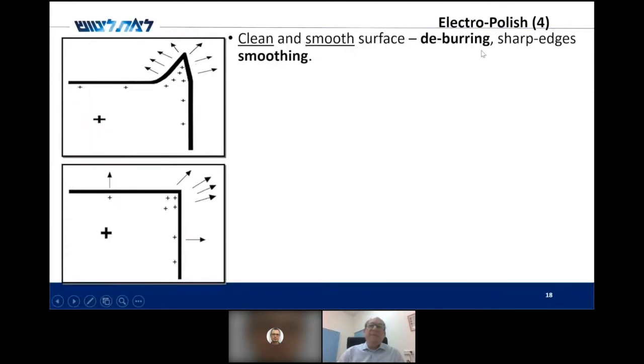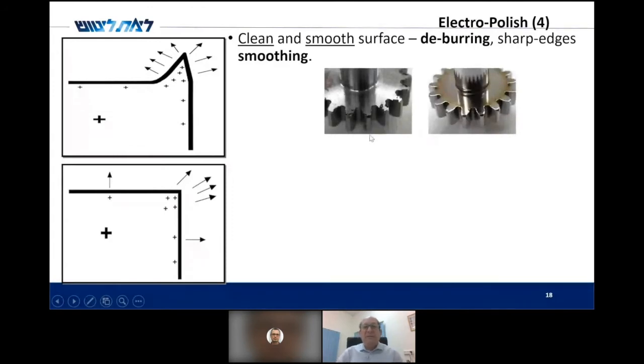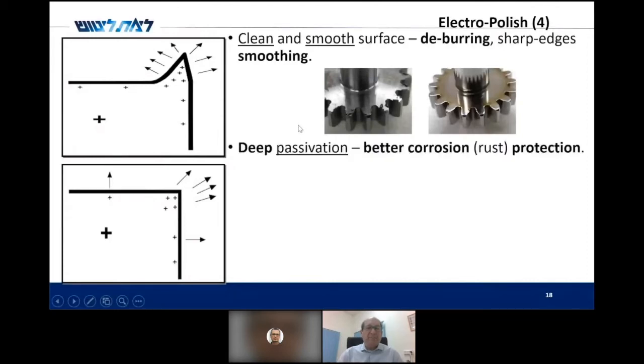One of the effects is the deburring, or taking away sharp edges and smoothing them. This is because the electrical field has a tendency to concentrate on sharp edges. This is an example of gears that you see here, the burrs of manufacturing, and after electro-polish they all disappear, while keeping the shape of each tooth as meant to be originally. This electro-polish also creates very deep passivation, better corrosion protection. I will discuss this later.